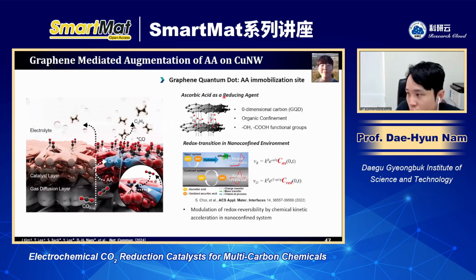And there is an issue when you apply ascorbic acid, because ascorbic acid is very easily dissolved into the aqueous electrolyte. So we had to find a way to confine this ascorbic acid on the surface of the copper as a heterogeneous catalyst. And we used some graphene quantum dots as ascorbic acid immobilization sites. By combining this GQD with the ascorbic acid, we could confine this ascorbic acid to the catalyst surface.